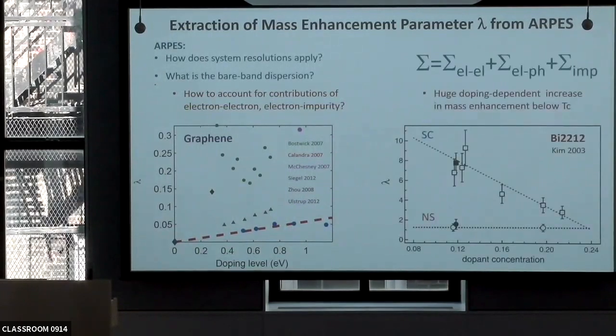I like to highlight what happens when you do have correlation by using the case of BSCCO 2212 once again. So this is a very old data set from 2003. What this is showing is lambda as a function of doping in BSCCO, so cuprates. Optimal doping is right here. If you start from overdoped and you look at the normal state, you more or less see an independent behavior. But as you start looking at the superconducting state, here's what you see. And so the message of this paper is a huge doping-dependent increase of the mass enhancement below Tc. But huge really means that this line is approaching the value of 10. And to me, this looks really unreasonable.